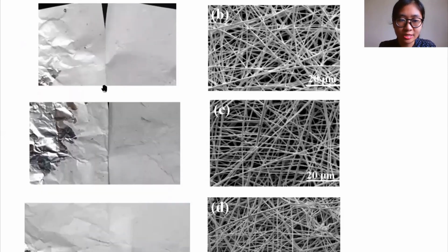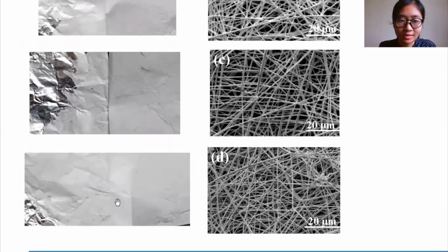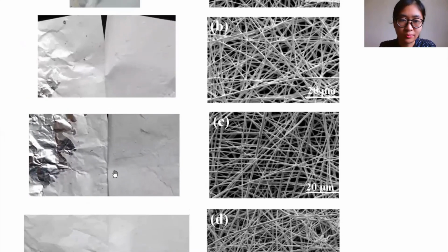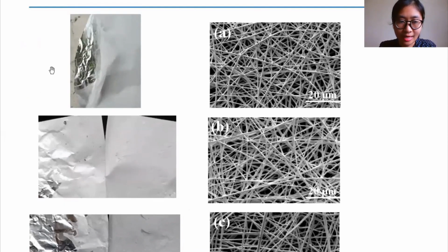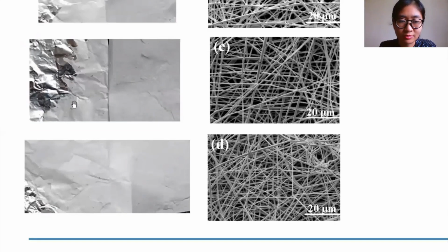For the PLA HHNT composite fiber mats, the fibers are not as observed and they have a much firmer structure compared to this one. As you can see, they're not peeled off totally from the foil, maybe because of the electric charge between the foil and the fiber mats.